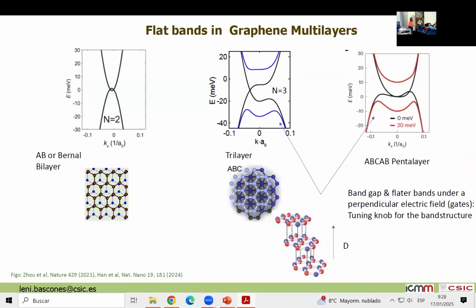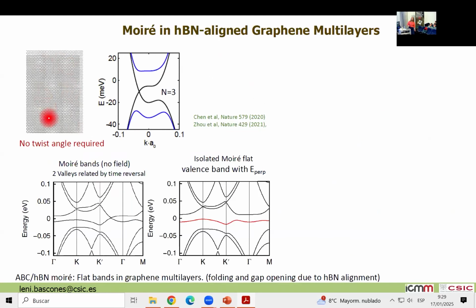And so people started considering a different type of systems, not only twisted bilayer graphene. So what people realized is that if you have a standard bilayer, trilayer, tetralayer, pentalayer, with a specific stacking, but so far without twisting. The one that you see here is what is called the rhombohedral stacking. So even without moire, you have the tendency to have in some region of momentum space some flat bands. The bands are a bit flat, just very close to the K points, but you see that there are some regions here that are quite flat. So if now we align this with the boron nitride, one can isolate these bands. Okay, so we can have moire flat bands without twisting.